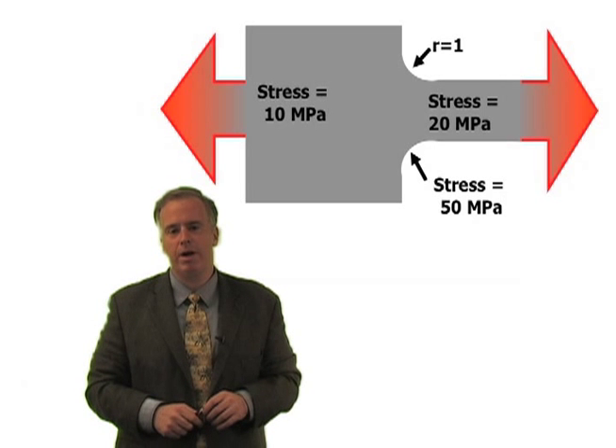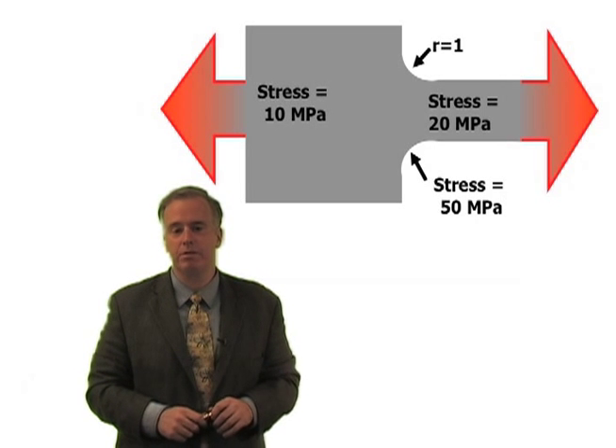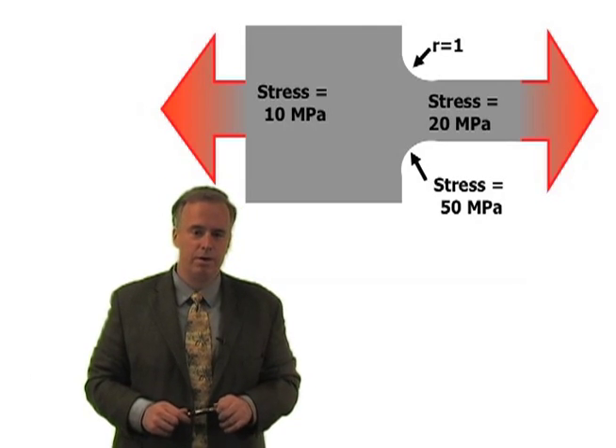And what we're going to find is then we can grind with our old parameters or maybe even a little more aggressive with a higher material removal rate and not have a risk of cracking that we had before.